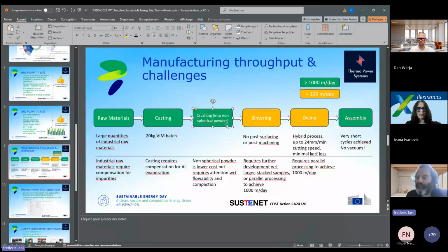Then, of course, we manufacture powders. What is best is to work with spherical powders for flowability and robustness of the compaction and then sintering process. We work with non-spherical powders because it's much cheaper. So we need to pay attention to how we dispense the powder in the next step of sintering.